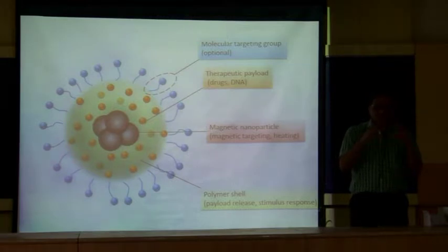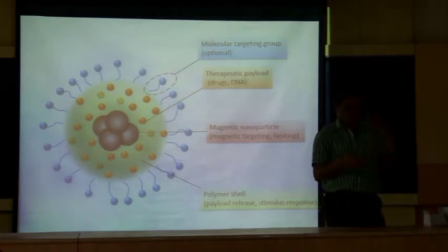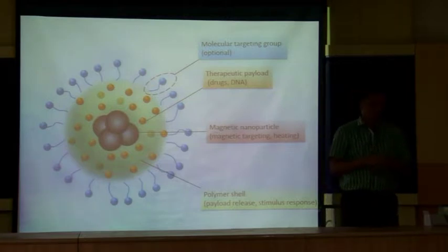So it collapses and whatever is in the polymer will be released on command. This is an important point. In other words, we can dissolve something in the polymer, and then when we want to, we can raise the temperature, it will collapse and release the anti-cancer drug.